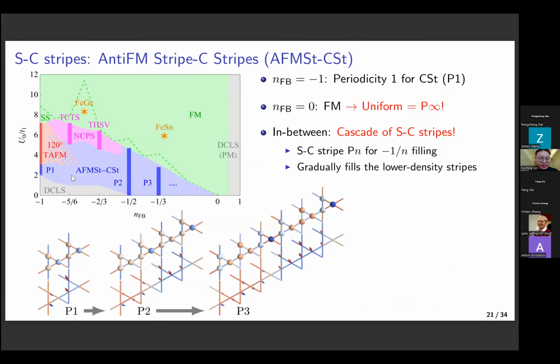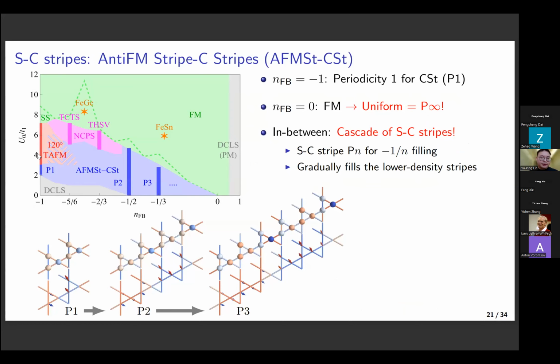So we have seen the spin and charge stripe in this region. And next I want to move a little bit higher in the repulsion and look at some non-collinear orders. For example, if we look at the -1 filling here, that is the empty flatband, we find that we can see a 120-degree triangle antiferromagnetism. That is, if we look at a spin sector, we can see that within a unit cell, we are seeing uniform spin orders. But if we look at 3 nearest neighbor triangles, we will see that the magnetic orders of them will form a coplanar 120-degree order.